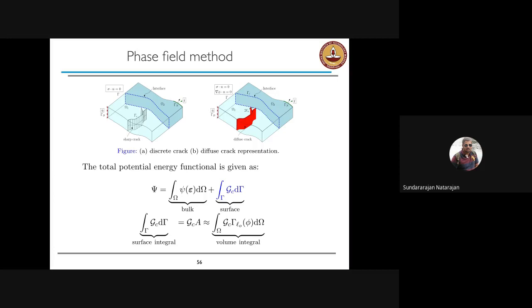And this bulk energy is a volume integral, whereas the surface energy is a line integral or a surface integral. And what we do is we use the Gauss divergence theorem to convert that surface integral to a volume integral. Then you can work with a variational framework to use the phase field model.